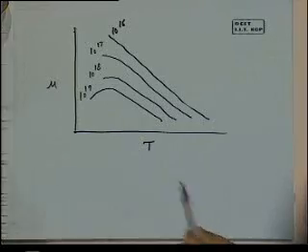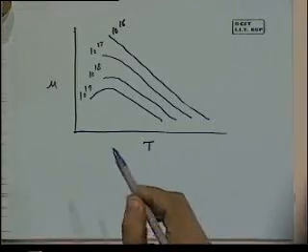The ionized impurity itself has a concentration with temperature dependence. But as long as we are talking about the saturation regime — where all dopants have become ionized — then there is no longer a temperature dependence from ionization. If you're in the ionization range, there is the additional temperature dependence coming from the ionization process.